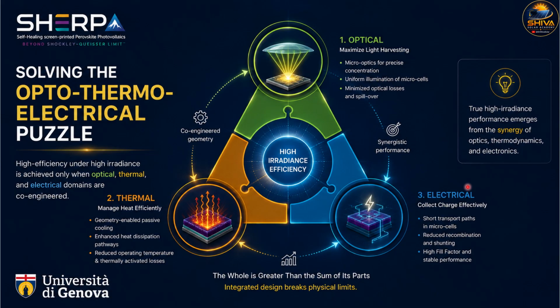This slide summarizes the complete strategy. At the top you can see the optical system, which uses a micro-lens array to precisely distribute and confine light onto the active regions. The thermal domain manages heat through passive cooling pathways enabled by geometry. This reduces operating temperatures and minimizes thermally activated losses. And the electrical architecture improves charge collection through shorter transport paths and reduces recombination.